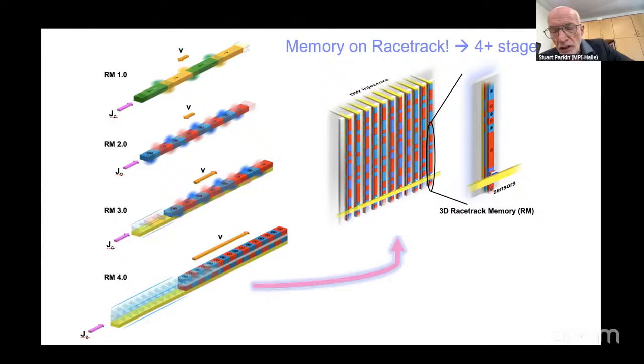So in racetrack 2.0, in cobalt, nickel, cobalt multilayers, we demonstrated we can move domain walls essentially in the same manner as in the soft magnetic materials. And they, roughly speaking, move at roughly the same velocity, about 100 meters per second, in the same direction, the direction of the flow of spin angular momentum derived from scattering within the magnetic materials. Racetrack 3.0 uses spin orbit torques by generating spin currents in neighboring high spin orbit coupling layers such as platinum. And now these domain walls move actually in the opposite direction for platinum because of the sign of the spin Hall angle. And they move nevertheless roughly 3 times faster, maybe 300 meters per second.